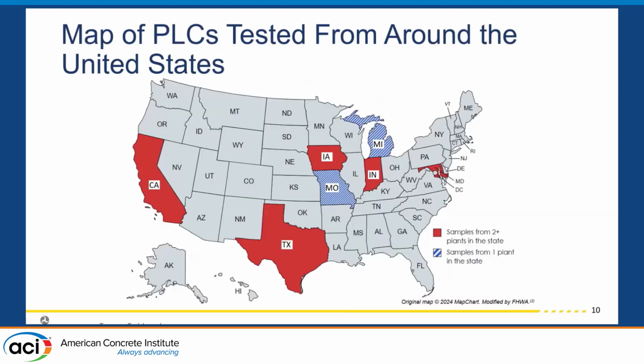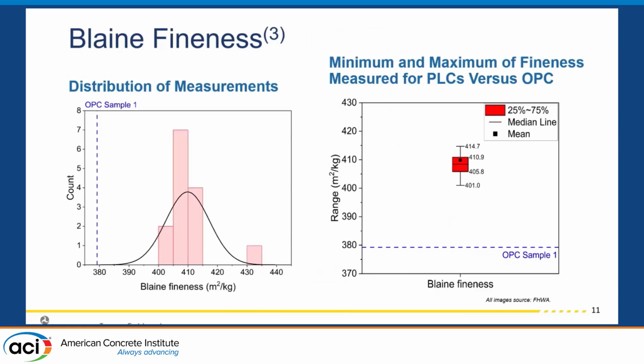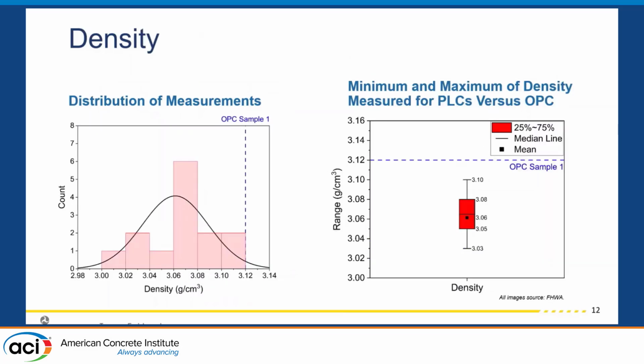In our PLC variability study, we looked at 16 different PLCs from around the country. You can see a map here of where those PLCs somewhat came from. Looking at our Blaine fineness, we saw a range in those PLCs from 400 to about 430, compared to our reference cement at 380. That's a little bit higher, which is what we'd expect to see, but there is a range there. Looking at density, we received density range from around 3.0 to 3.12, and our reference OPC cement is around 3.12. So again, we generally have a lower density in our PLCs compared to our OPCs.